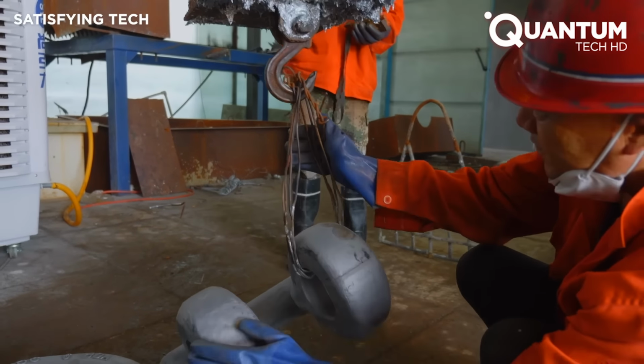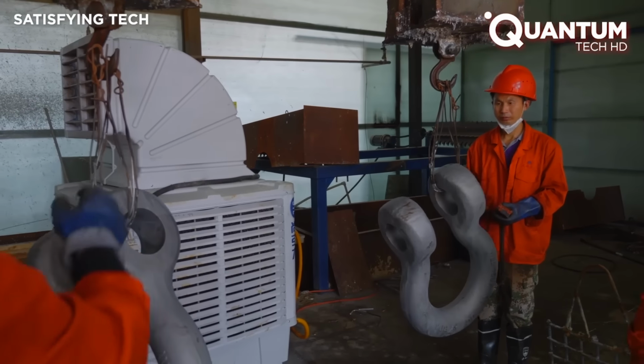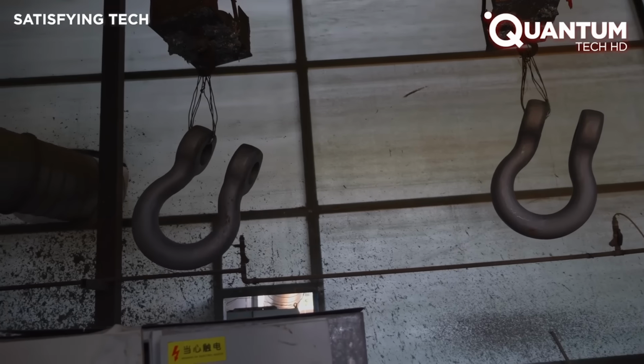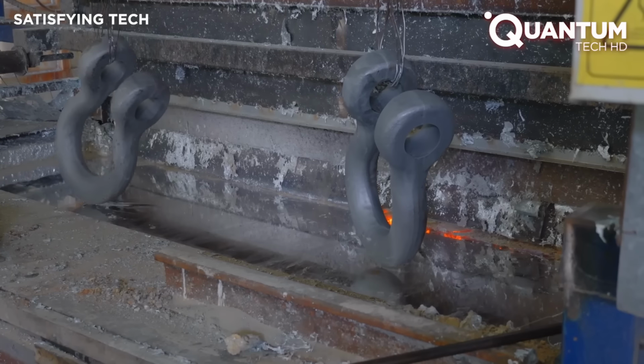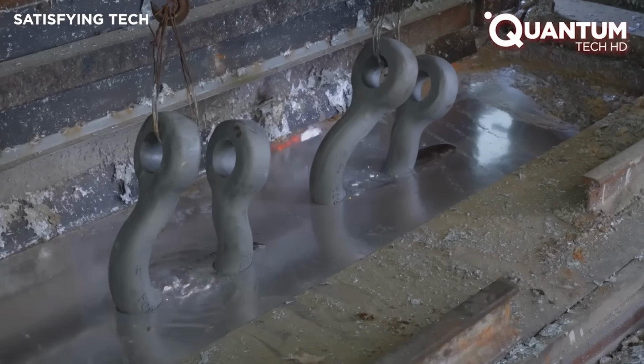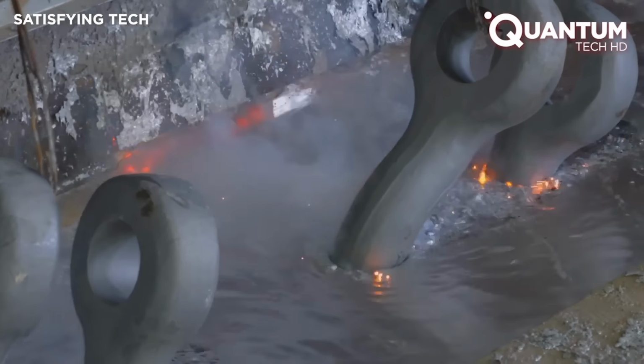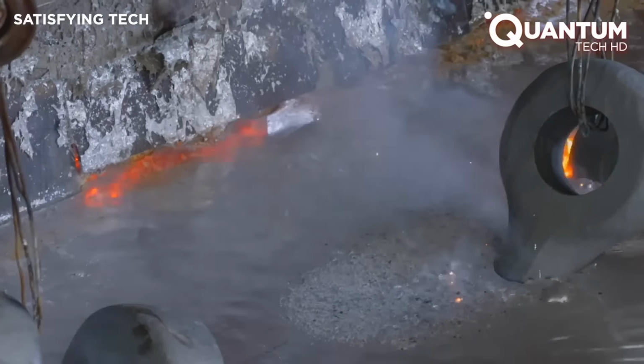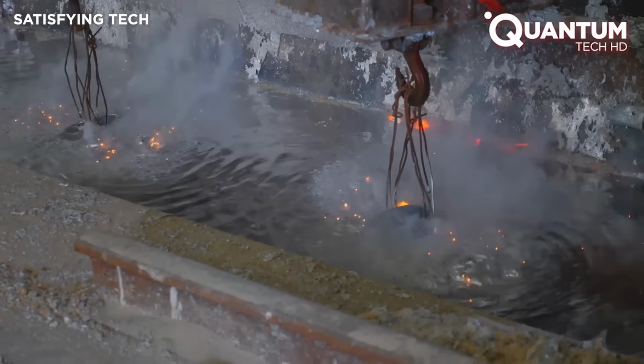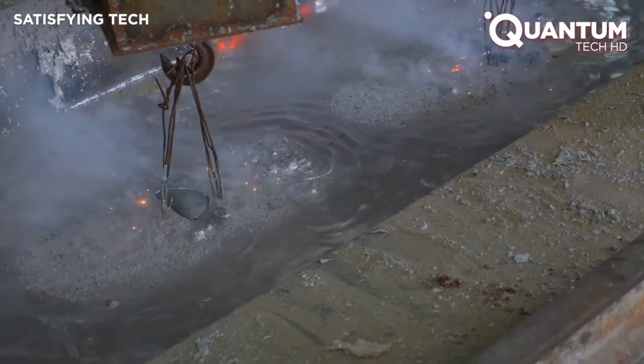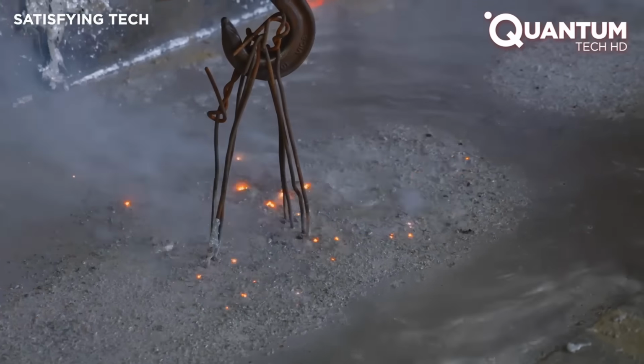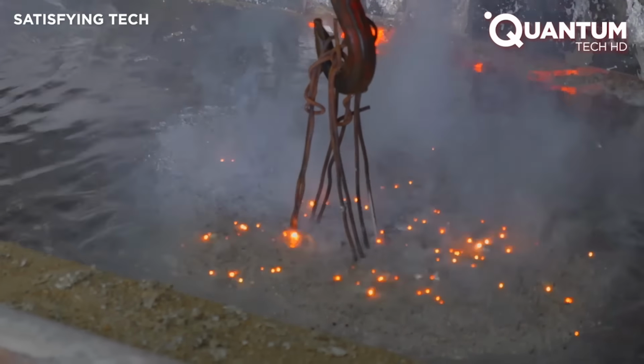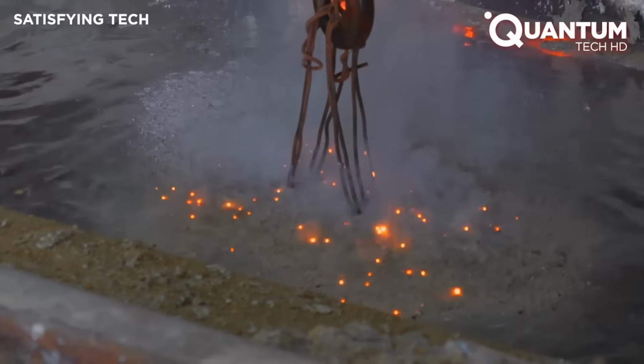Salt water is relentless, and even the most resistant steel would rust within months without protection. To protect them, each shackle is immersed in a bath of molten zinc. The contents of this bath alone are valued at $100,000. At over 800 degrees Fahrenheit, the zinc bonds with the steel, forming a resistant silvery coating. This is hot dip galvanizing.